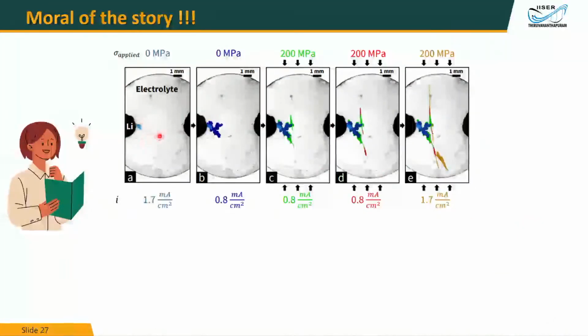So you have a small amount of lithium coming with zero pressure applied. You can see this is tending to grow, and with 200 megapascal of pressure applied, you can see that it's starting to deflect. And again with 200 megapascal, it's starting to grow in the deflected direction. And again with more current and the same pressure, it's even going to the sides, and it's never trying to reach the other side.